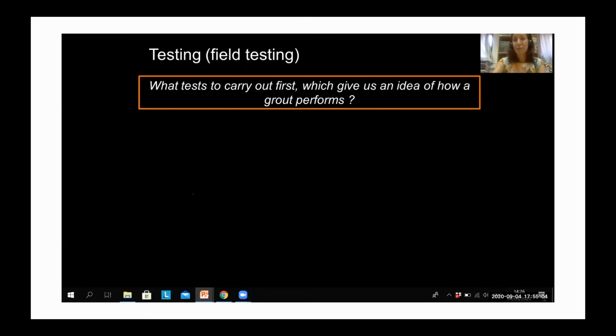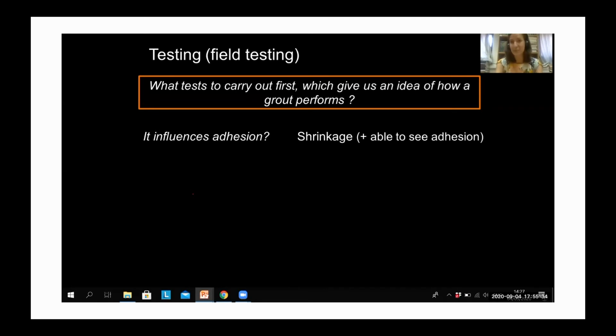So talking about field testing, starting simple, even if you're in your lab, in order to assess if a grout is broadly promising or not. What tests to carry out first, which can give us an idea of how a grout can perform? Of course, this is not a rule, but this is what I feel is mostly useful to know at the beginning, where for sure shrinkage, because if a grout shrinks, it doesn't work. And that will also influence adhesion.